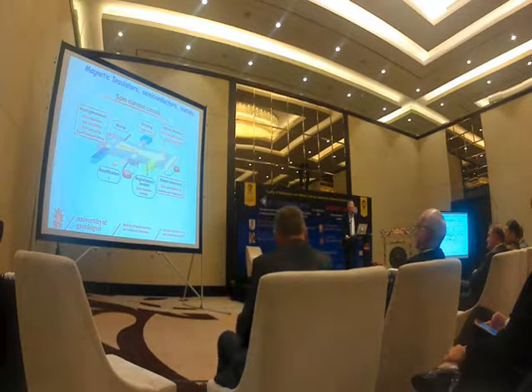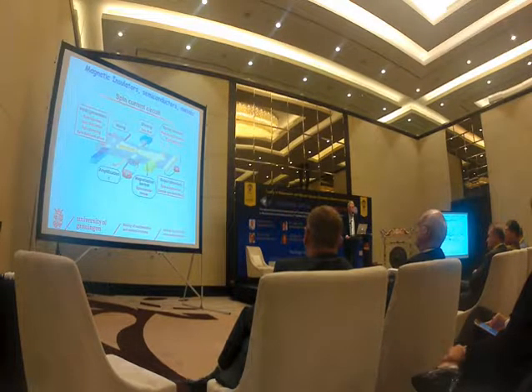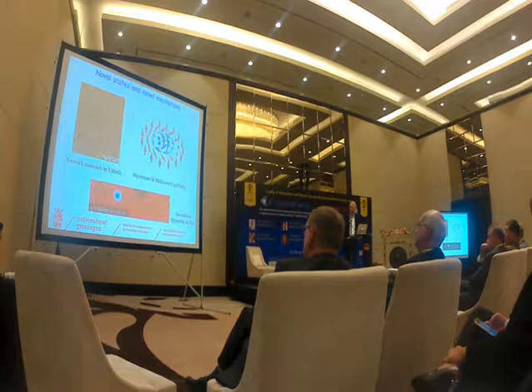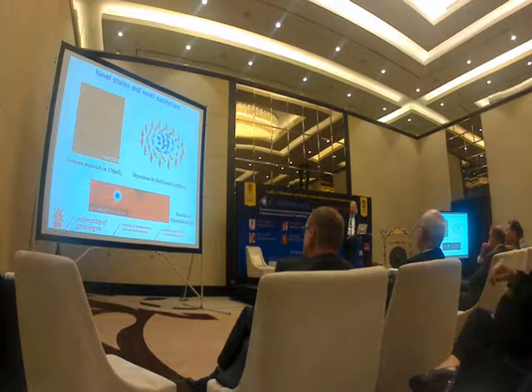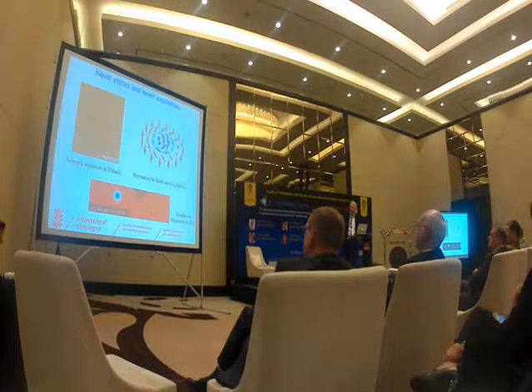Now, these spin currents, they exist in materials of only very special nature. And one of the possibilities is not to make use of symmetry, but to make use of topology of nature. An example that I can give is a spin excitation that is no longer just the value of spin up and spin down, but where you see topology, that is the networked information of such a spin current, and the spin in the middle acts as, the object acts as an excitation, it acts as a particle. It is conserved, so that means that you can transport it without any loss of electrical charge, or any means of electrical charge. And this is an example where you see the motion.